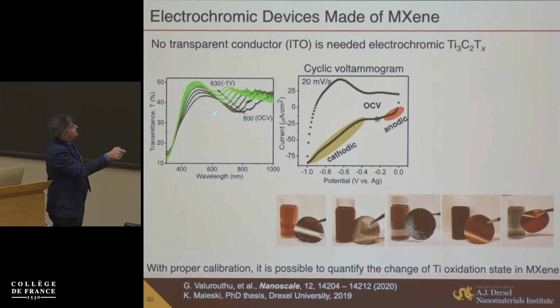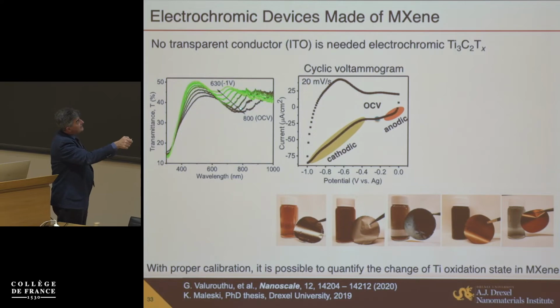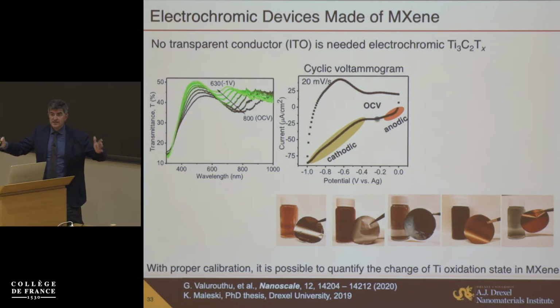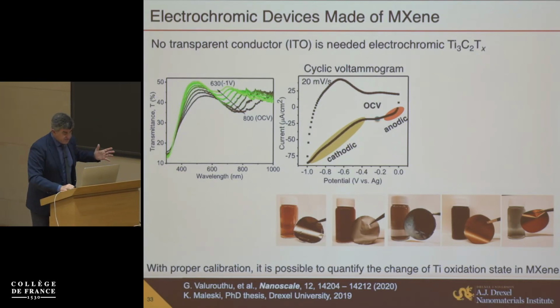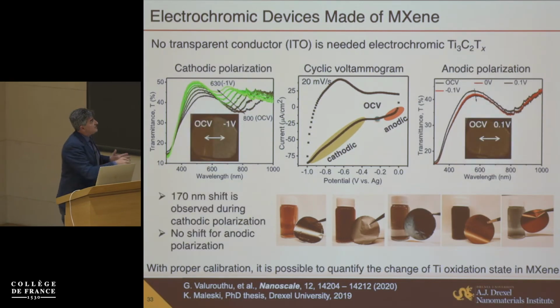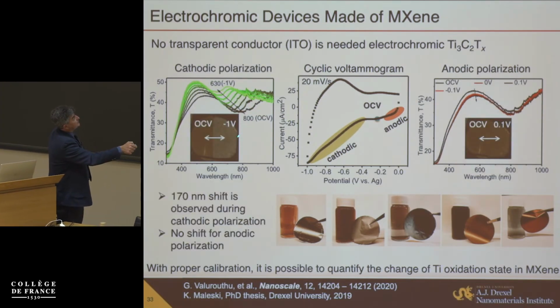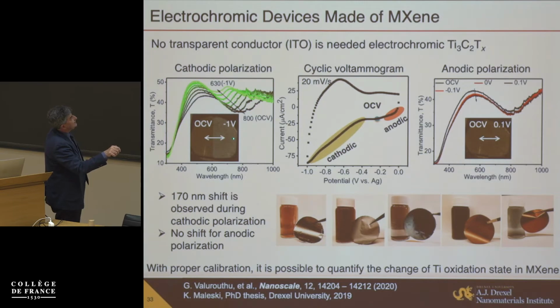When we apply potential of -1 volt in sulfuric acid electrolyte, from OCV we go from about 800 nanometers to 630 nanometers. So we have a 170 nanometer change in the peak position. It's very visible actually. The film will visibly change between green and blue. It doesn't reproduce colors extremely well on my screen, but you can basically see it here: green at OCV, and it becomes blue at -1 volt.